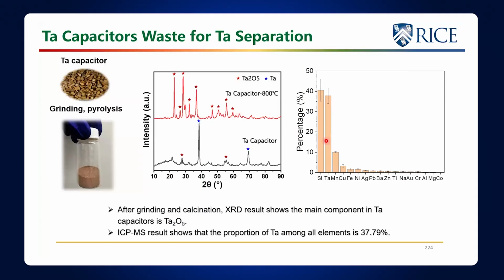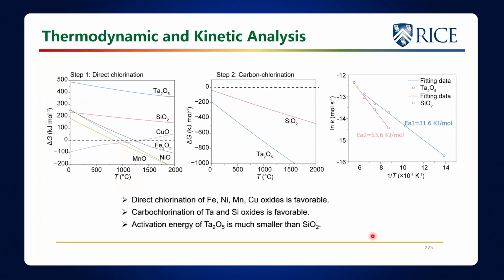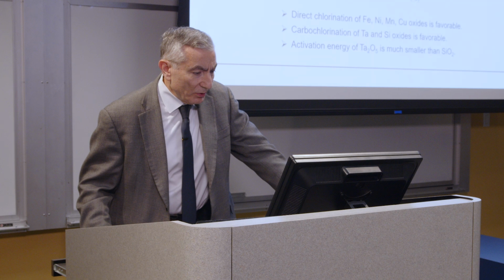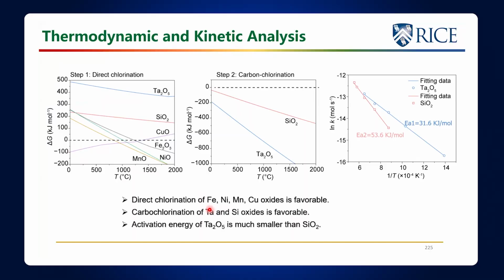Thank you. It's mostly silicon, but it's still a high percentage, like 37.79% of that residue is now tantalum. And so here's the thermodynamic chart. Consider this: if you do the direct chlorination, what you'll do is you chlorinate the iron and the nickel and the manganese and the copper. So in this region, you're going to chlorinate all of these, right? Because all of these are below zero. And that's going to leave silicon and tantalum.